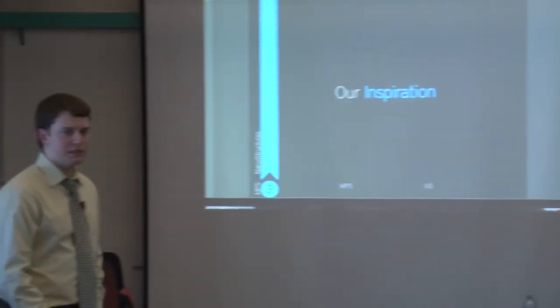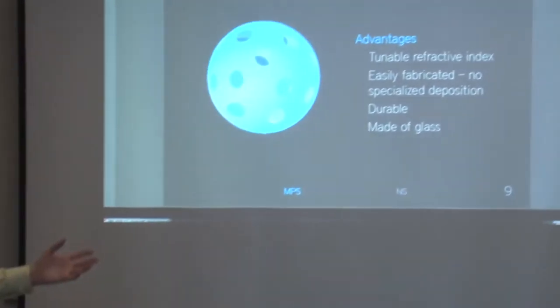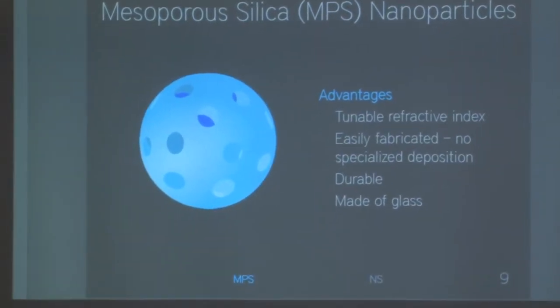The inspiration for our project came from two different materials: a nanostructured substrate and mesoporous silica nanoparticles used to coat the substrate. Mesoporous silica is tuned by the thickness of the layer to work for a specific wavelength — on its own, it is an anti-reflective coating but not usable for a wide range of wavelengths. Mesoporous silica is essentially like a hollow glass foam, and we can add different ratios of binder solution to increase the refractive index, making it tunable between 1.12 and about 1.5.